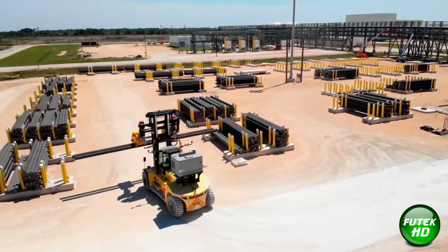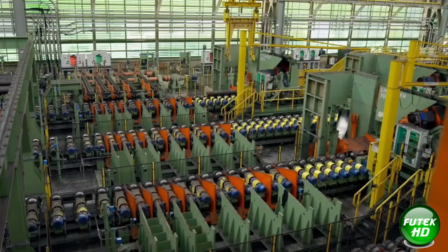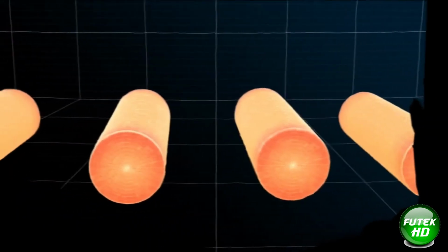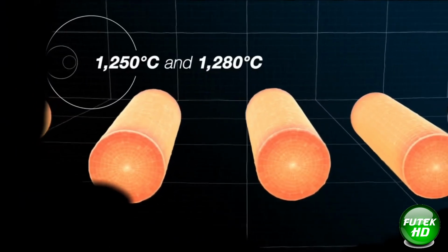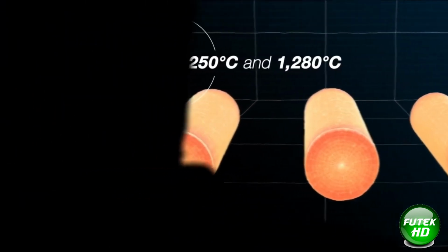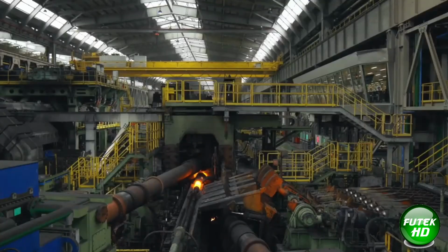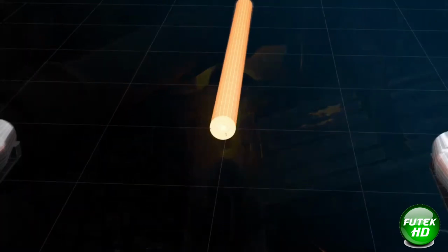In the hot rolling mill process, billets are heated to 1,250 degrees Celsius to 1,280 degrees Celsius in a rotary hearth furnace. The Mannesmann effect, named after the Mannesmann brothers, involves using a barrel-type piercer to transform the heated solid steel billets into hollow blooms.